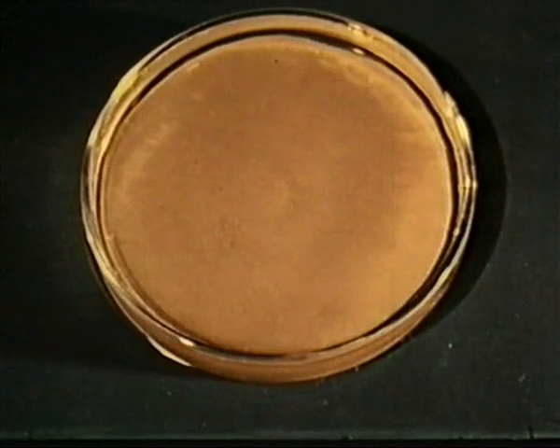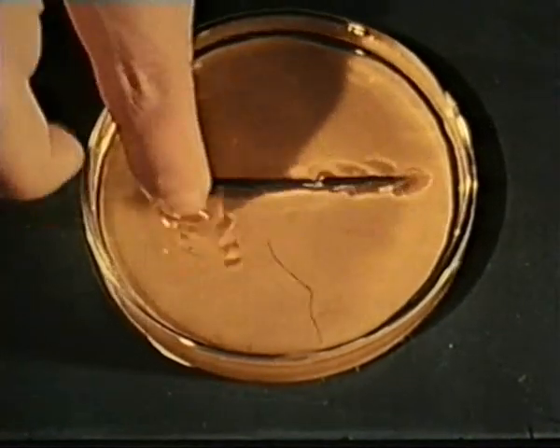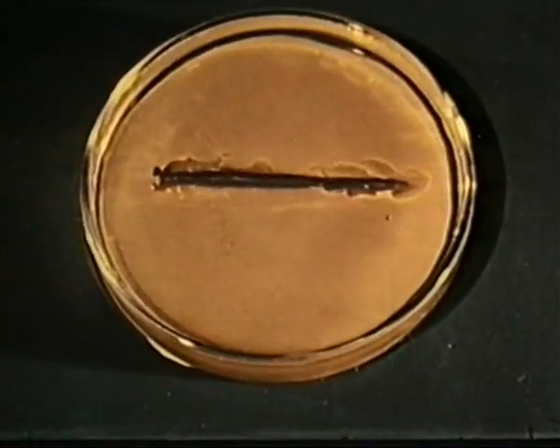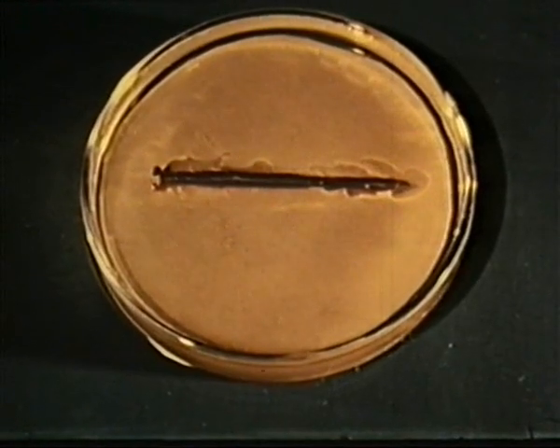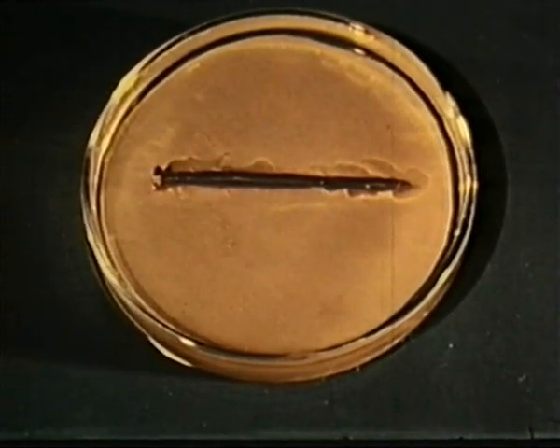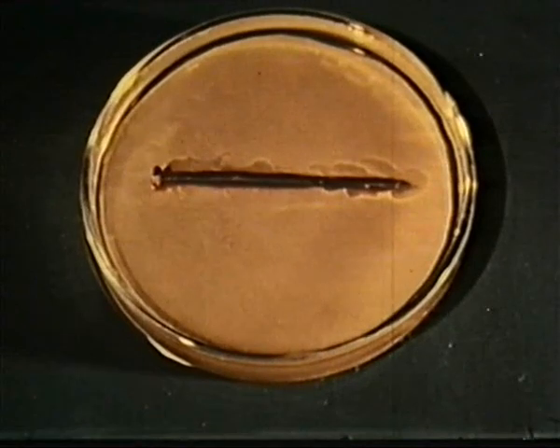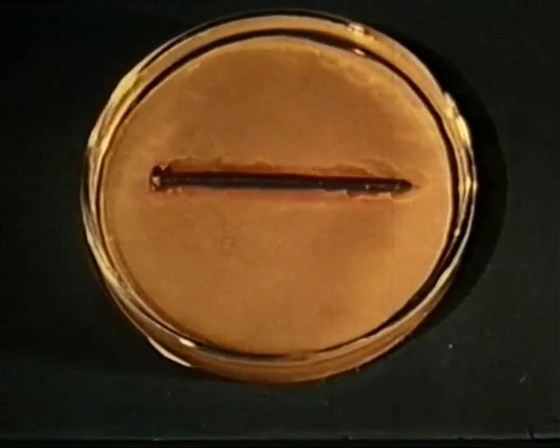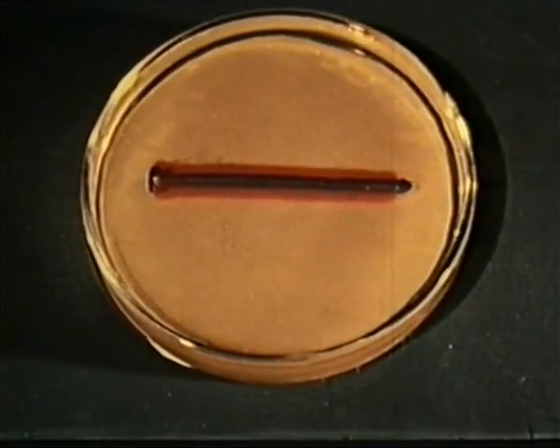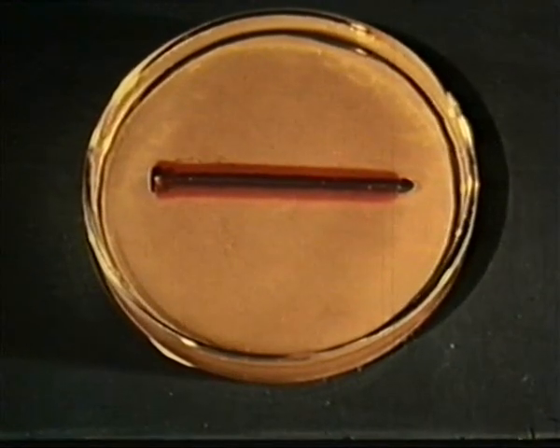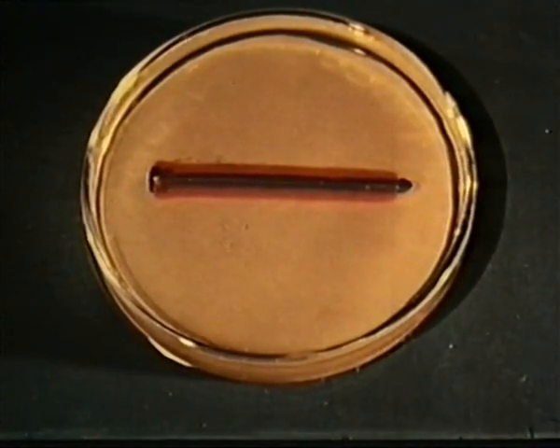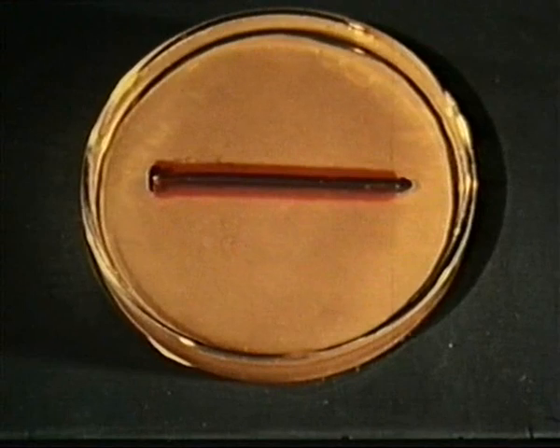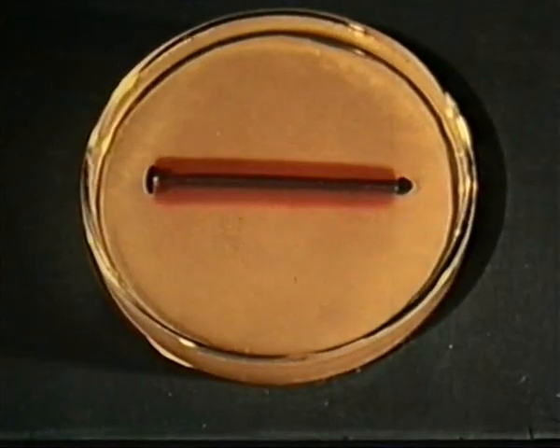A similar technique may be used to show a local action cell on a single metal surface by placing an ordinary iron nail in a prepared gel. After several minutes, a pink area develops around the shank of the nail, indicating formation of a cathode. Blue areas develop around the cold-worked head and point of the nail, where the iron goes into solution, indicating that these areas are the anodes.